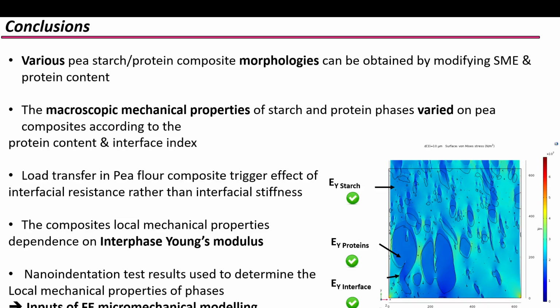So to conclude, we have seen that various pea starch-protein composite morphologies can be triggered by using a quite interesting combination between the SME and the protein content. From the macroscopic viewpoint, the 3-point bending test reveals that we could achieve a high variability in terms of behavior, ranging from brittle to elastic-plastic behavior. We have also seen that the load transfer at the interface in these composite materials has more of an effect on the interfacial resistance than on the interfacial stiffness. And these were confirmed by more local mechanical properties, which allow us to determine the interface Young's modulus.